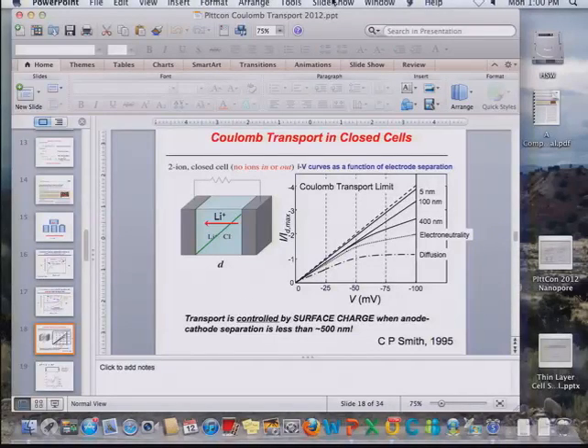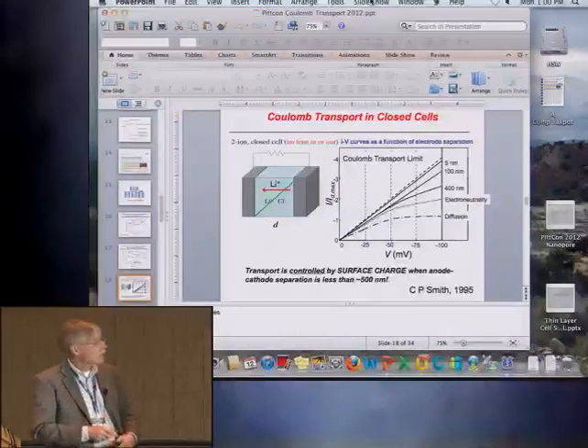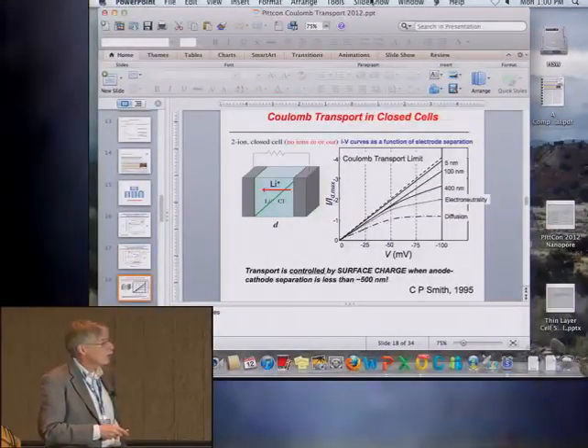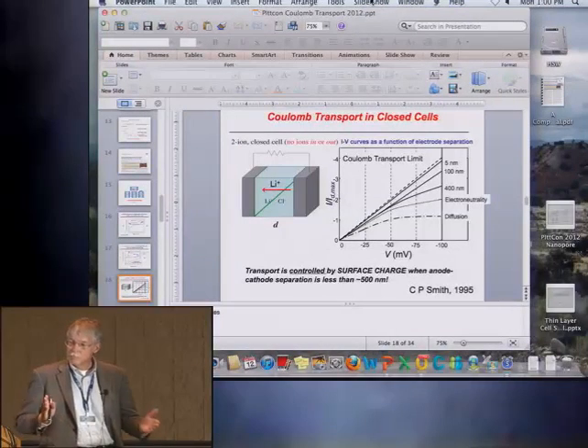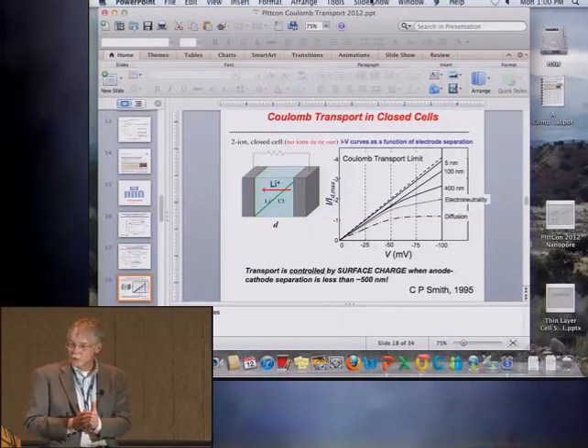Here are the current-voltage curves: normalized current versus voltage, 0 to 100 millivolts. This is the voltage we're applying to the cell. Here's the diffusion-limited current, the sigmoidal-shaped curve. If you start pushing the electrodes together, this curve starts to straighten up, going down to 5 nanometers. And at 5 nanometers, you reach the asymptotic limit. What's interesting is that at 100 millivolts, the current has increased by a factor of 4. So it makes this interesting in thinking about making cells thinner and thinner for energy applications.